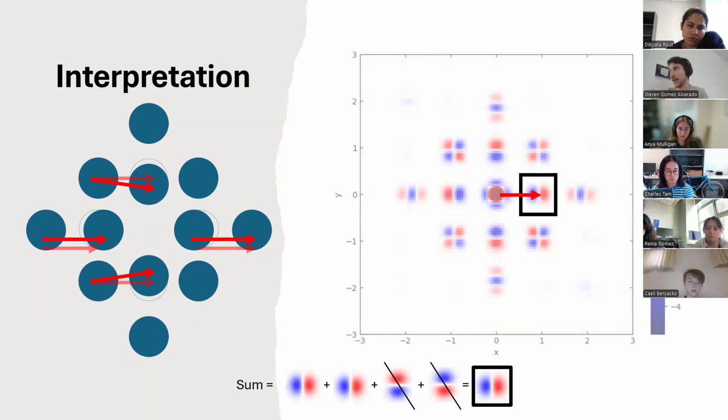So that's why I'm looking at pairs where at least one of the atoms has moved. Okay. Then I also have to think about what I'm seeing in the PDF: every single one of those sets of pairs superimposed on the same coordinate, because we lose all information about what atom was at the origin when we do the PDF. Okay. So we're not just seeing one atom or one pair of atoms, we're seeing every possible pair of atoms that exists where they're 1 unit cell apart.